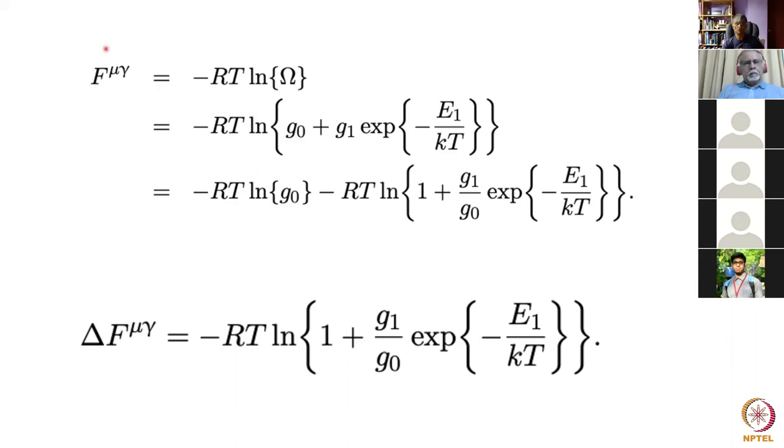So if I want to work out the difference in energy between the state where all the atoms are in the ground state and then at a particular temperature T, then this term disappears here. And that is our difference in the Helmholtz free energy, okay? So that is the meaning of a partition function: how the atoms are distributed over the different energy states, how they are partitioned on the different energy states. And the importance of that is that we can take the logarithm of that function, multiply by RT, and we get the Helmholtz free energy term